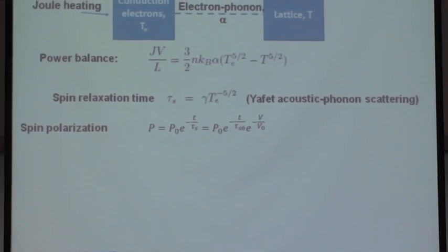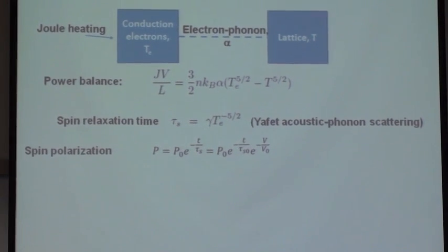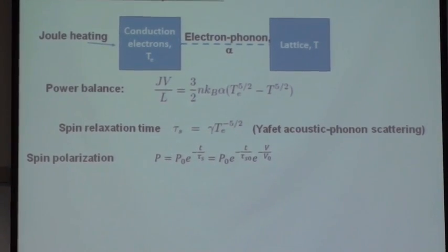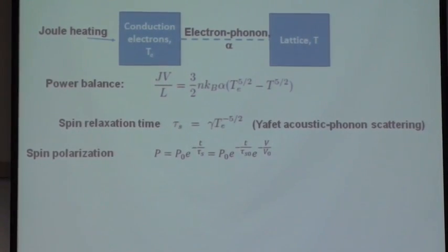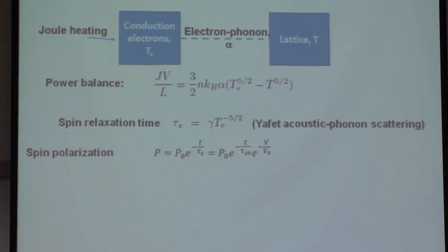So in other words, the effect of heating the electrons with the electric field would be that instead of just shortening the time scale for transport much shorter than the spin lifetime and saturating the resulting spin polarization, you actually start to depolarize the electrons due to the electron heating effect with a characteristic voltage scale V0 here.